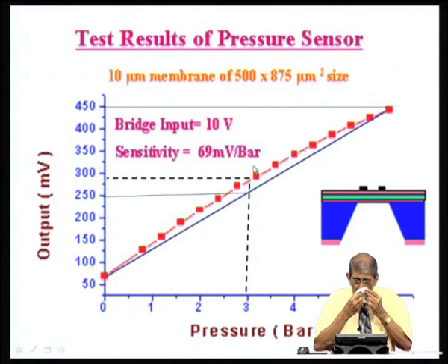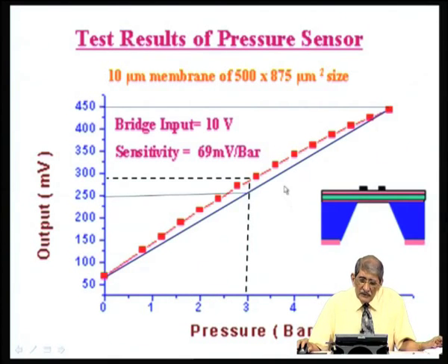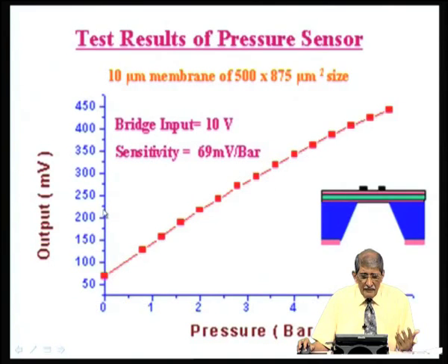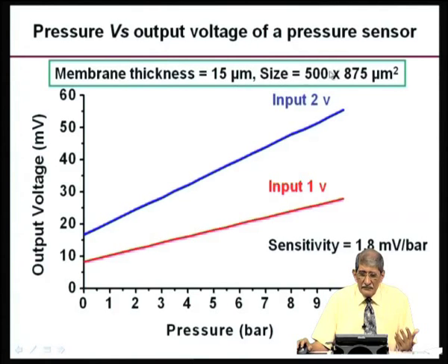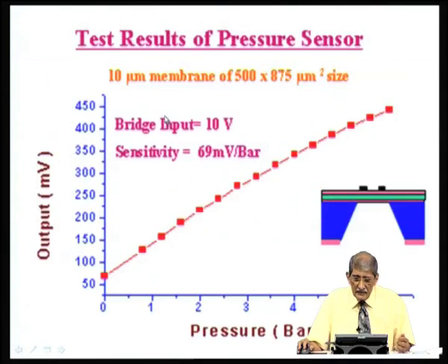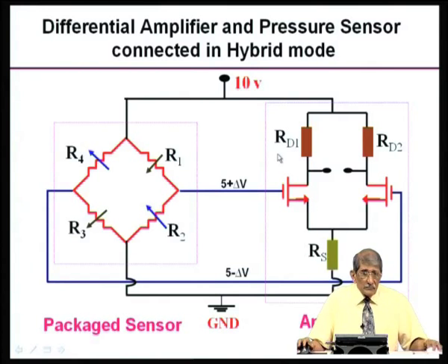So, this type of device you can use only up to about 3 bar pressure. If I use up to 3 bar pressure, the non-linearity all over this range will be less than about 1%. Okay. So, one would recommend this sensor with this thickness and these dimensions for use only up to about 3 bar. If I want 10 bar, I recommend 15 micron thickness with that dimension. So, for higher pressure with the same lateral dimension, the membrane has to be thicker and thicker. Okay. Now, quickly going through the integration.